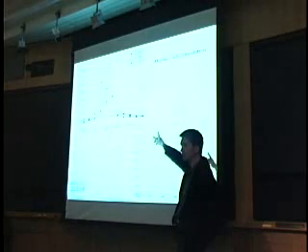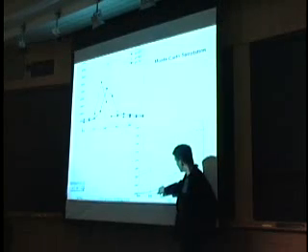If you didn't draw the lines here, but just the points, that peak is essentially defined by 1 point, the green one. You should always be careful, you may have very spurious behavior going on in a similar Monte Carlo situation. The other peaks have slightly more points, but normally if you really wanted to know whether it's first or second order, you would refine it a lot more near the phase transition. Again, the energy seems to be continuous, but don't let the lines fool you. You've taken these points and connected them, so of course they're continuous.